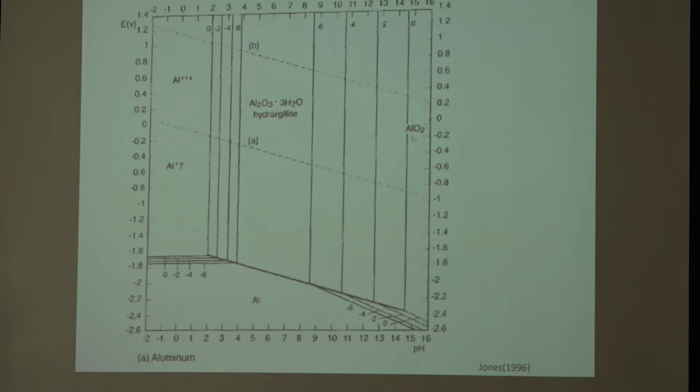It's AlO2, and that is going to corrode. It's not going to be stable, and it's happened on a number of projects, people using aluminum for railings, things like that, and after a while they have a lot of localized corrosion where it meets with the concrete. It does depend a little bit on the pH of that grout. If it's close to 10, it's all about your potential here. So if you're far enough from the higher pH, if you're close to 8, 9, 10, you may be okay. But there is a limit, and unfortunately, a lot of people find out after the fact.